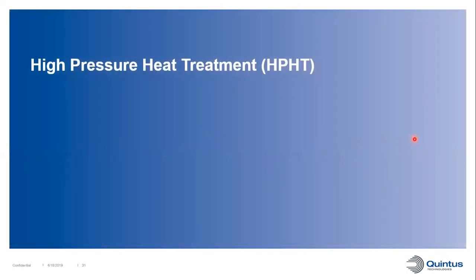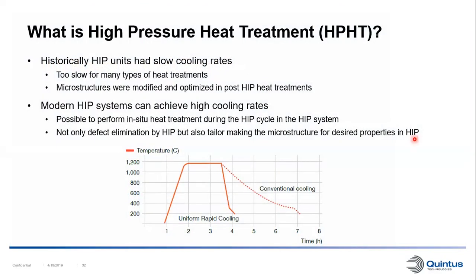Now I want to talk about something we call high pressure heat treatment. So historically, HIP systems had very slow cooling rates. The cooling was achieved just by shutting off the furnace and letting the system cool down by itself. And that could take many, many hours. So conventionally, heat treatment was not possible to do in the HIP process because of these slow cooling rates. They were not high enough to heat treat materials with good results.